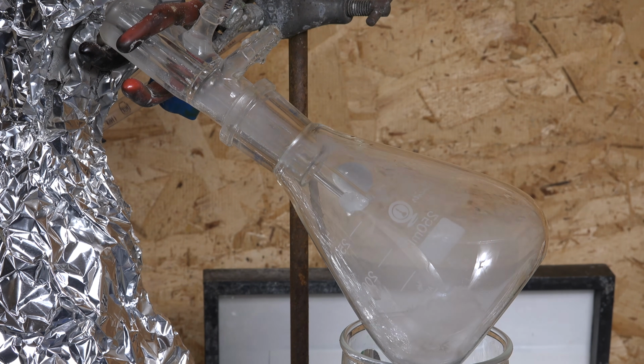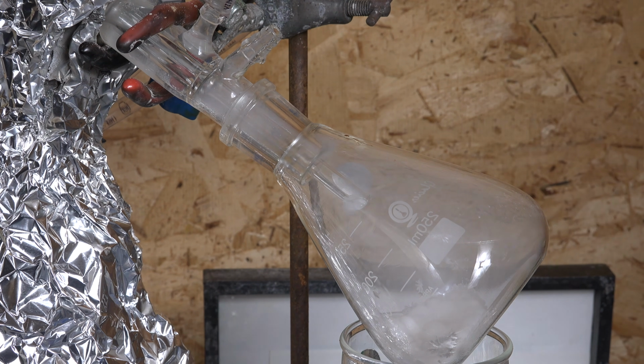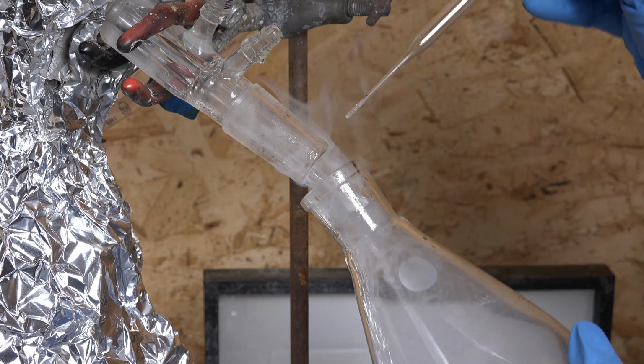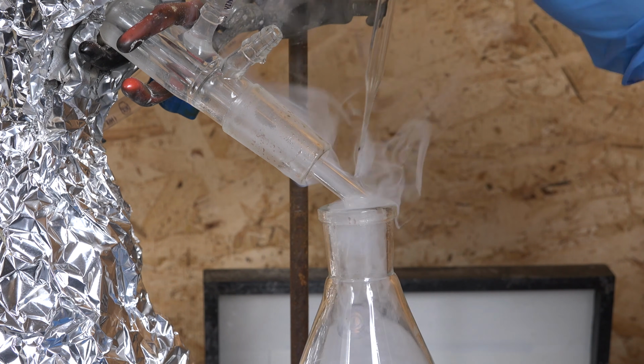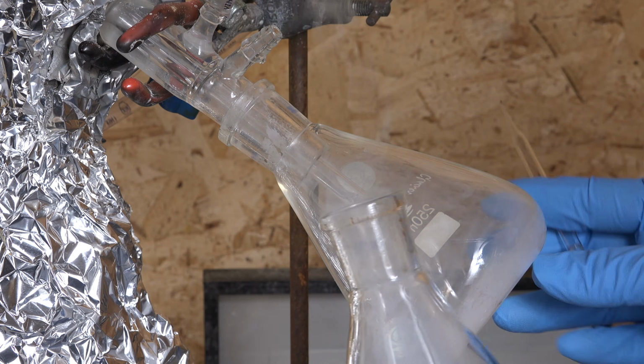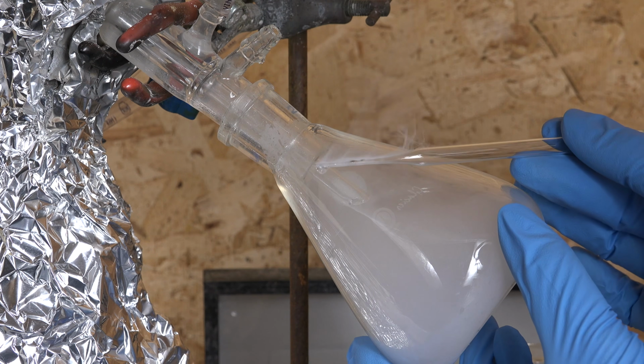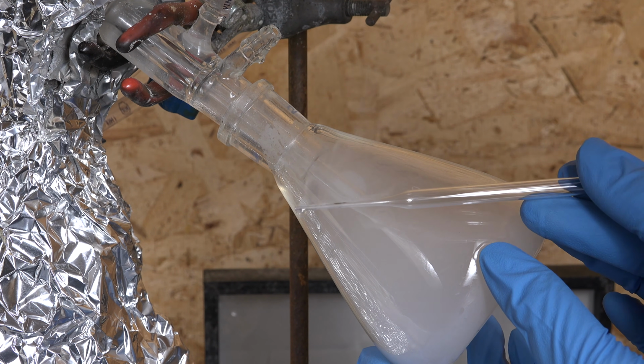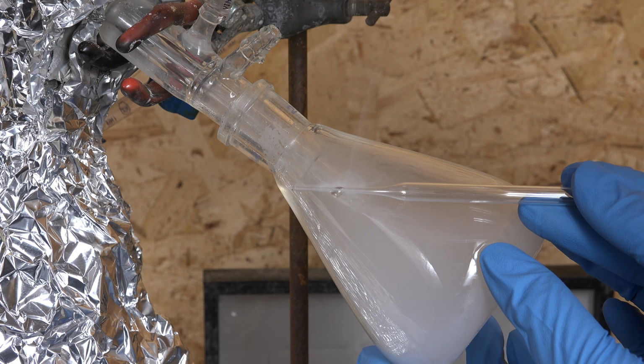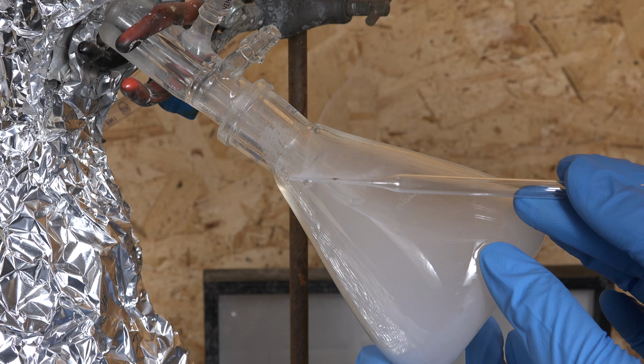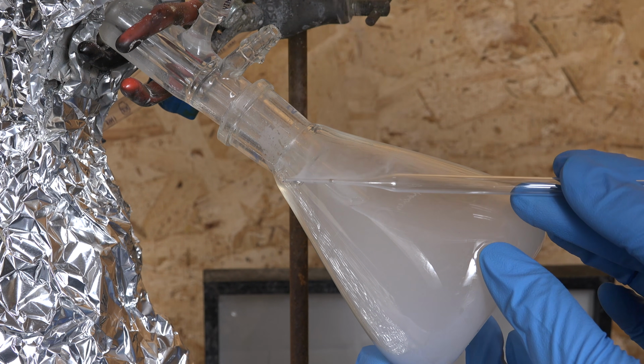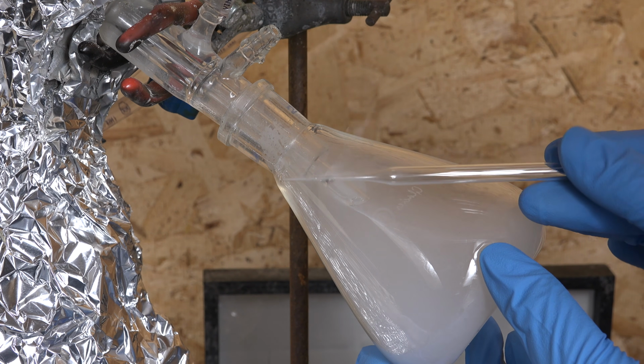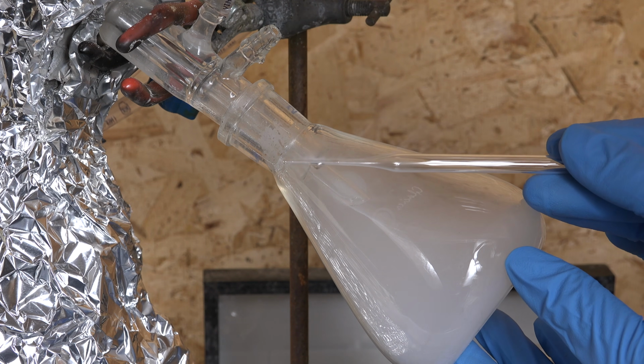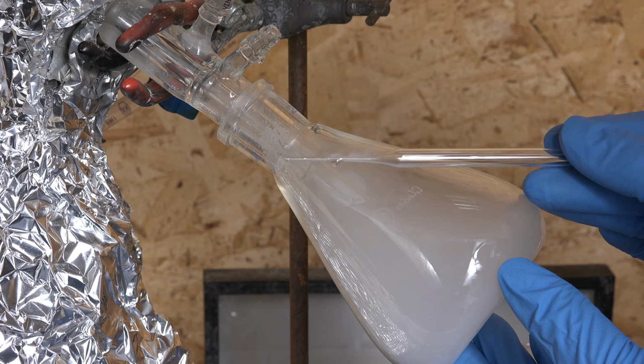Anyway, after another half hour, it's starting to shrink again, indicating the distillation is transitioning to sulfuric acid. So I changed out the receiver, and since the solid sulfur trioxide is pretty small, it seems a lot easier to push off with my pipette. I also did the fume and solidification test again, where I held a drop on my pipette to see if it would solidify. And again, it remained liquid, indicating we're transitioning to sulfuric acid. And fuming seems to be minimal. So the test does seem to work, but admittedly it's not the best test. It's a little dangerous to be waving around a highly corrosive liquid, but at least it's better than no test.